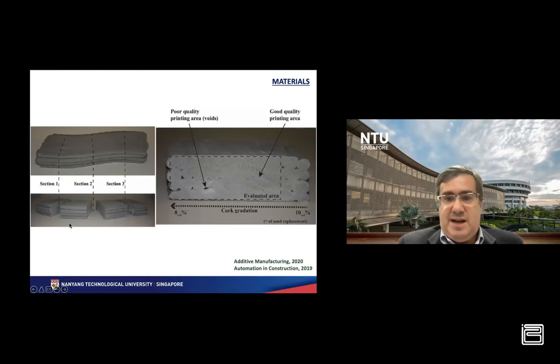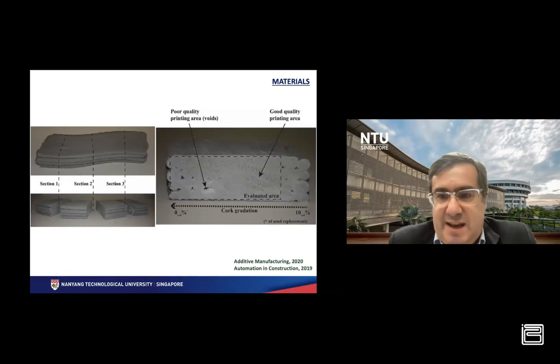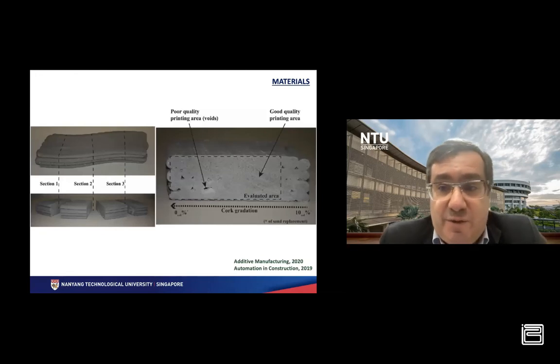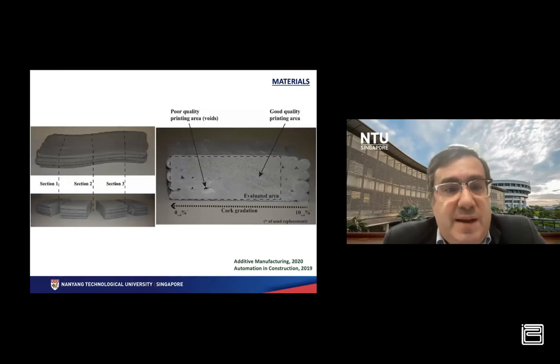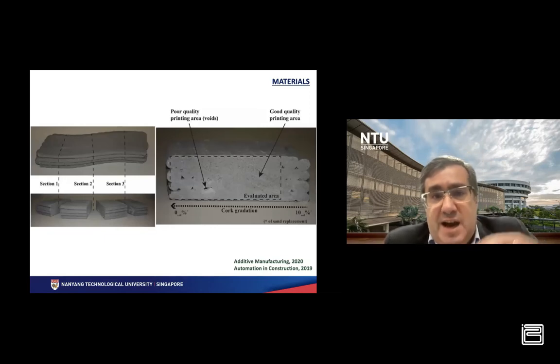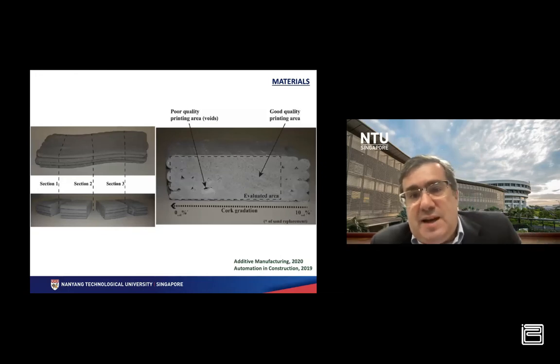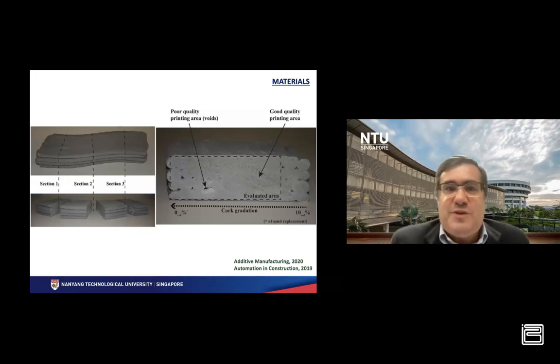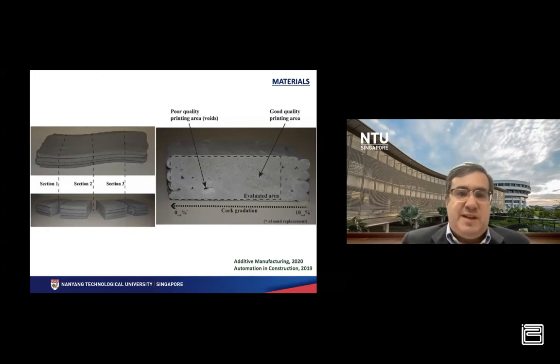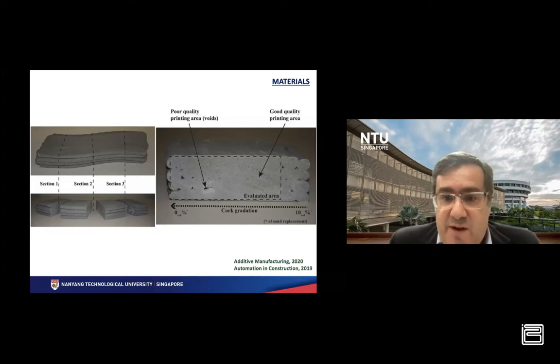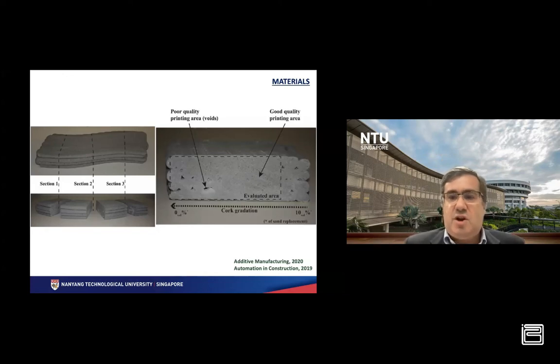So it was a structure where we started printing using only concrete, and we ended with concrete containing 10%, and later we increased to 20% by volume of cork. It is possible to reach high values. The only limitation that we had was the pumps, so we need to invest more money to improve the printing capabilities. But we can increase the amount of cork added to the concrete material. More expensive pumps are required because by increasing cork, we increase significantly the viscosity of the materials.